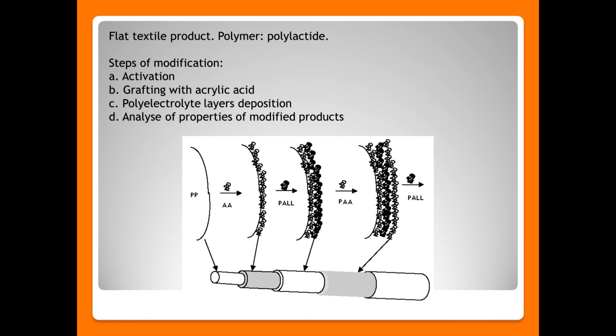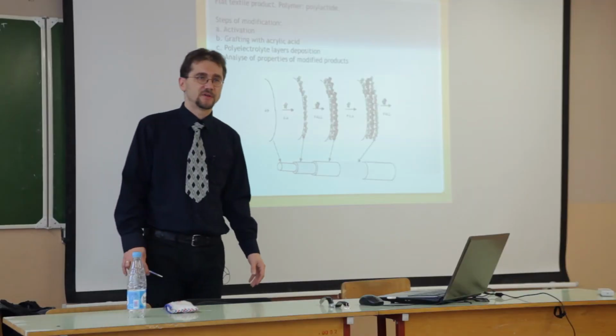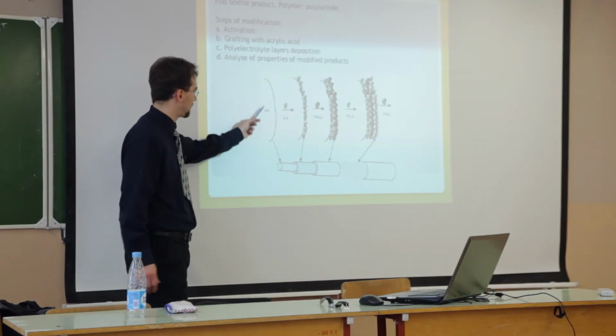Of course, we started not with polylactide, because polylactide is not such an easy material. We started with polypropylene, which is the easiest material. The surface structure is very regular, and the modification should be easy. So we started with polypropylene.